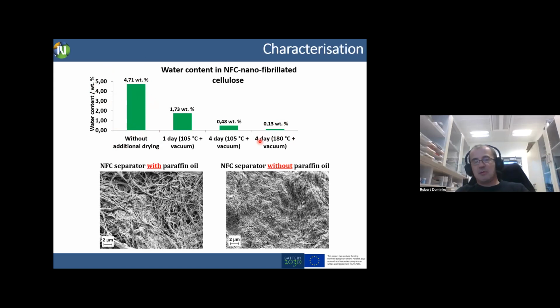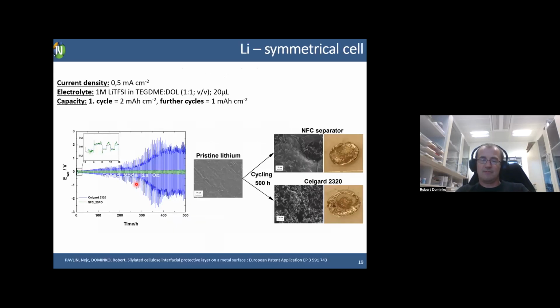And then the next problem comes when you deposit cellulose with the wet laying procedure, which is used in paper technology. Paper technology wants to have a less porous system, but we need some porosity if we want to have electrolytes filling this porosity and to have some kind of conduction. That's why we also started to use paraffin oil, which created porosity and gives us a nice playground to adjust porosity and thickness and so on.